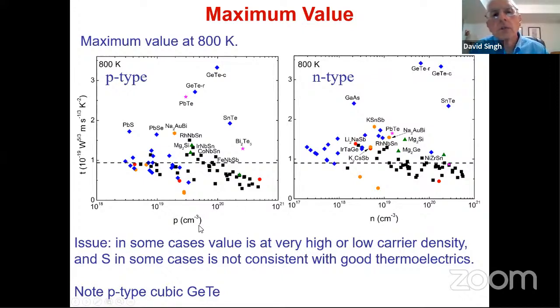This is carrier concentration, but what we did was we calculated T at 800 Kelvin for P-type and N-type materials. And we calculated it as a function of doping level, and then took the highest value and plotted it here. So this is lead telluride. This is the value of the carrier concentration where it occurs. Remember, this is a higher carrier concentration than people experimentally did in the 1960s, but it's very close to the one that now is thought to be optimal. So T gives you this optimal carrier concentration, and we plotted it.